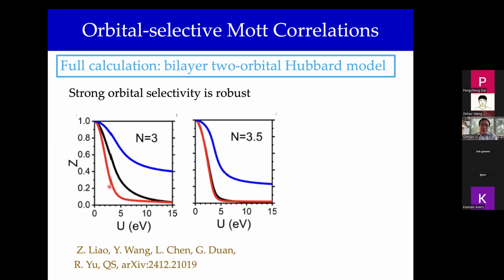To gain a wider perspective, and also to put other cousin systems into the mix, such as the trilayer nickelate, which has since also become available, in the model calculation we allow ourselves to go away from the physical n equals 3 electron filling case and say this is n equals 3.5. Qualitatively, similar features persist. The differentiation between the renormalization factors, the correlation effect in the 3dx squared minus y squared orbitals versus the 3dz squared orbitals.